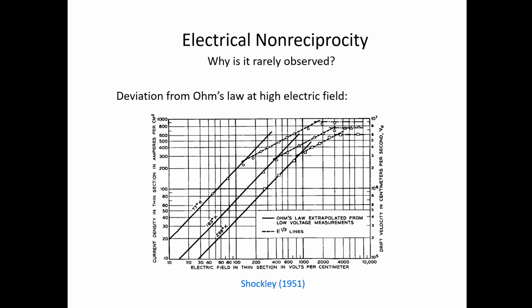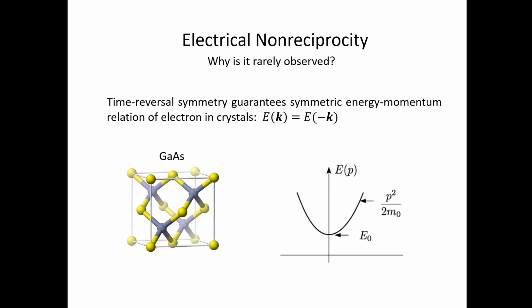Okay, so the question is why this non-reciprocal IV relation is so rarely observed. One thing to notice is that a nonlinear IV curve itself has been observed a long time ago. This is from the Bell Lab days, the early days of semiconductor research. As you increase the input voltage, the IV curve deviates from linear. But still, in this material, which I think is germanium, the IV curve is reciprocal. If you reverse the direction of the voltage, the current just gets reversed. There's no second order nonlinearity.